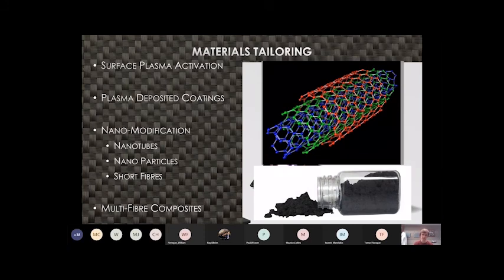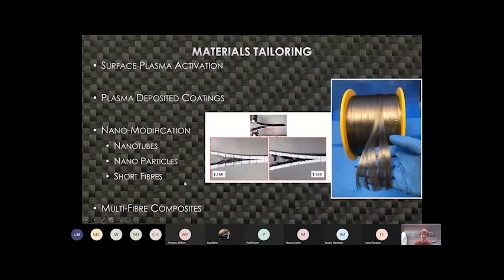Something which is actually ongoing here is the application of steel fibers into composites. This would be combining these with a traditional carbon fiber composite, for example, and has been tested quite extensively and was shown to increase the fracture toughness of a composite. In the middle here, you can see a DCB test being performed. By adding just a few layers of this steel fiber into your carbon fiber composite, you can dramatically increase its toughness, making it very, very resistant to impact in particular. So this is something that could potentially be applied into wind turbines for, say, bird strike protection and that sort of thing.